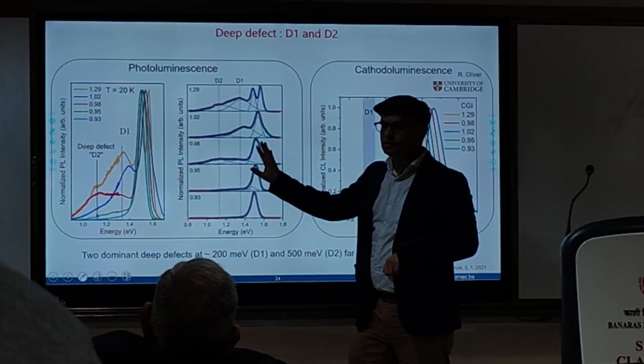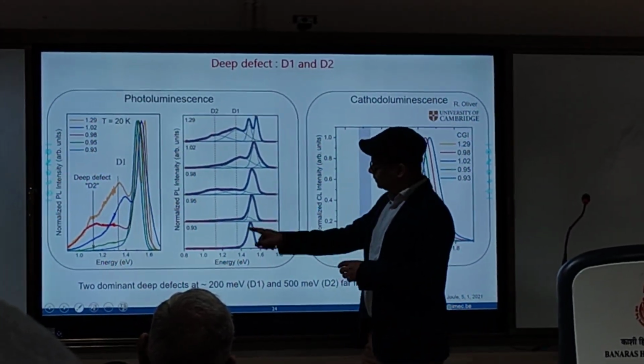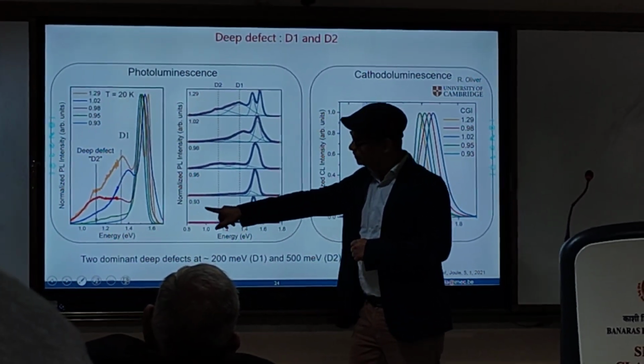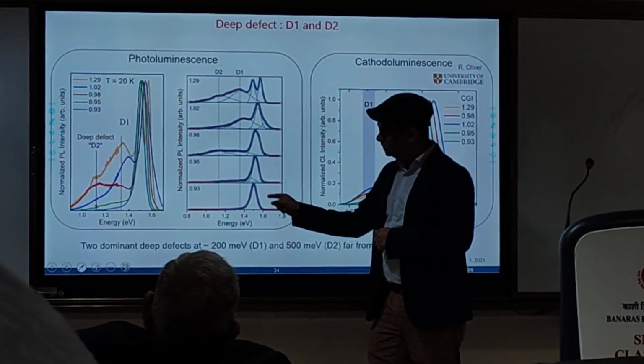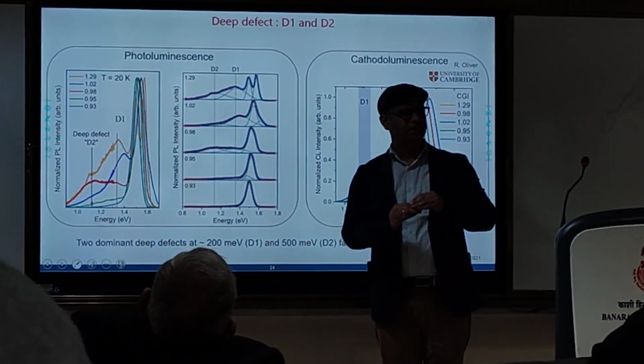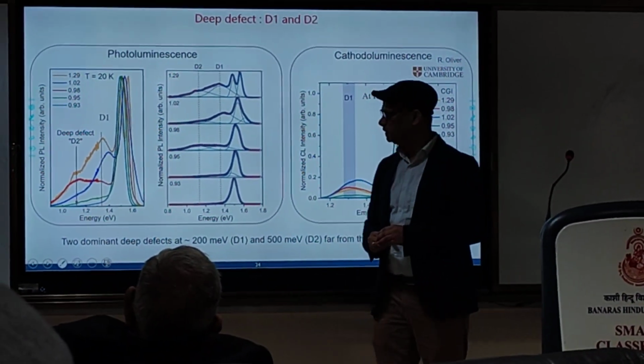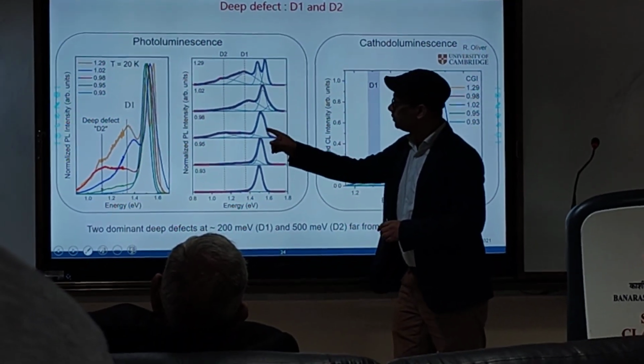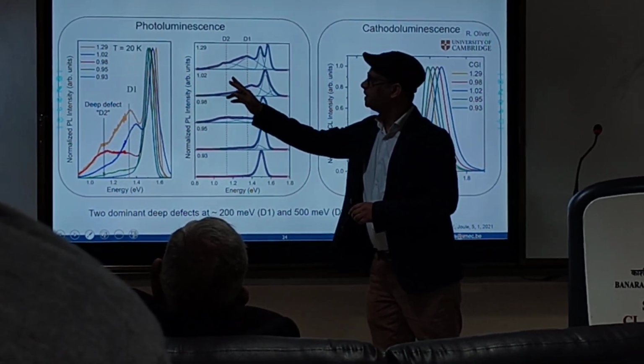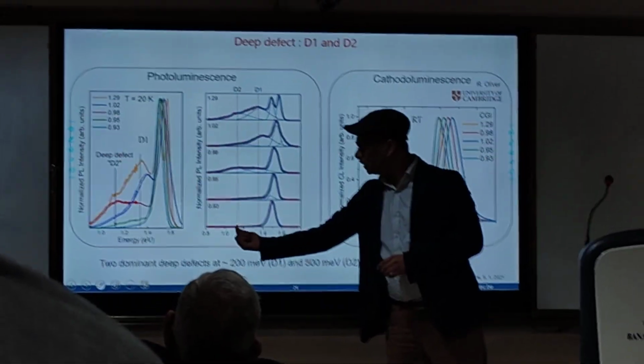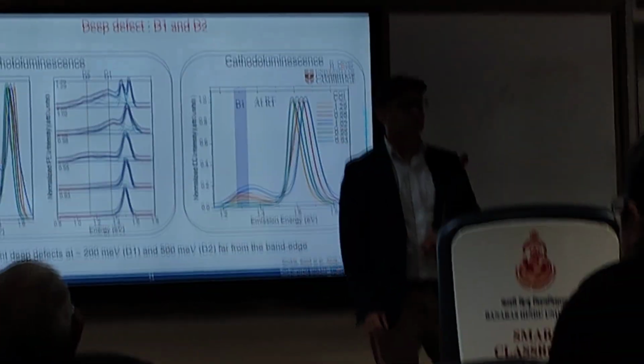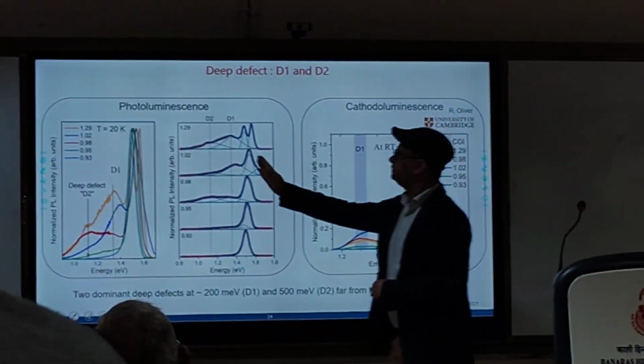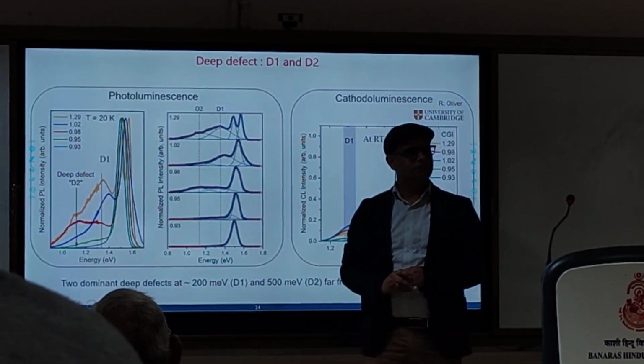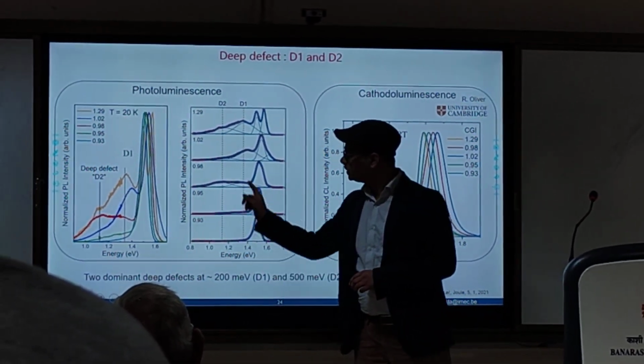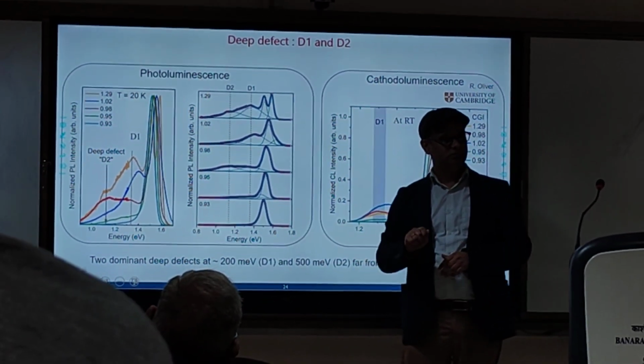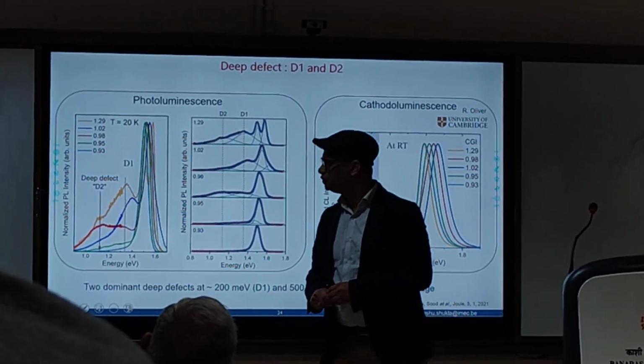Let's look at this one first, because this is essentially the same thing. This is the copper-rich film, and this is the copper-poor film, because the ratio is less than 1. You see there is just one peak coming up, corresponding to the band edge transition, which is the band gap of the material. As soon as you make it more copper rich, you see some of these peaks appear at low energy. Actually quite low energy, 200 to 500 millielectron volts. So these are deep defects, which are present in the copper-rich film, but if you make it copper poor, you can actually get rid of them. So composition acts as a knob to tune the defect.